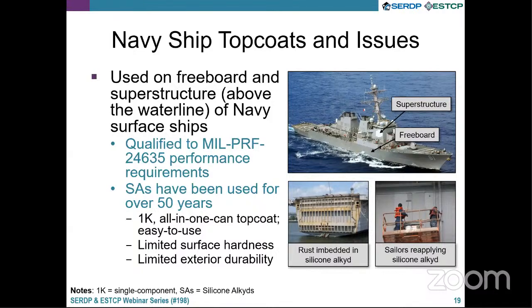So any running rust coming down from protrusions on the ship, such as I show in the photo here of the stern gate, would become easily embedded within the surface of the coating. These silicone alkyds would also easily chalk and degrade after 6 to 12 months outside in the sunlight. Because of that, their exterior durability in general would be reduced, and that gray color would begin to fade to a lighter gray color over time, and sometimes even to a pinkish color, depending on the pigments that were utilized.